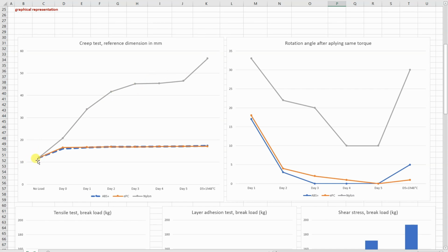It started from 12 millimeters, and as you can see the ABS and polycarbonate almost didn't creep at all, until the nylon had a continuous creep, and even here the last point is after placing in an enclosure at 48 degrees Celsius. And this is that screw creep test, rotation angle after applying the same torque, and the perfect is 0. So here we can see that after maybe 2 or 3 days the ABS and PC don't creep at all, while the nylon is continuously creeping, even here, and especially after placing it inside the enclosure at 48 degrees Celsius.